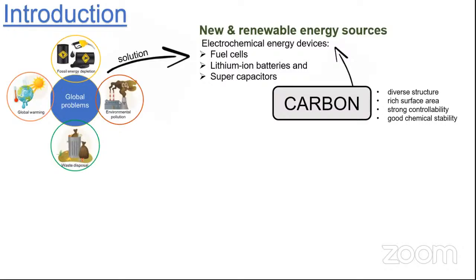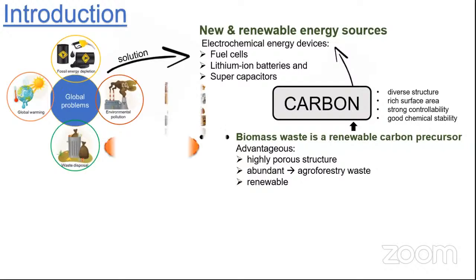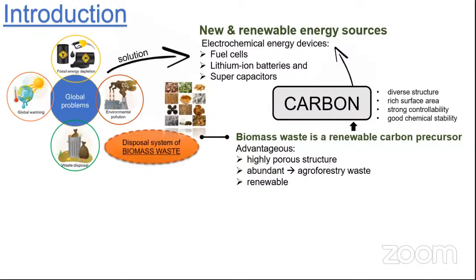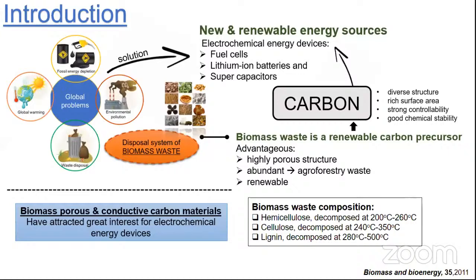The use of biomass waste like coconut waste as carbon precursor is also a great approach in waste management and pollution control strategy. The advantages of biomass waste as carbon precursor are that it has a highly porous structure, and is abundant and renewable. We utilize coconut coir, which is an agricultural waste product generated in large quantities in Indonesia, to generate a value-added product. Biomass-based material generally contains lignocellulose compounds like hemicellulose, cellulose, and lignin that degrade at different temperatures and produce a carbon material as their residue. With some treatment, biomass waste, including coconut coir, can be converted to porous and conductive carbon material that has attracted great interest for electrochemical energy devices.